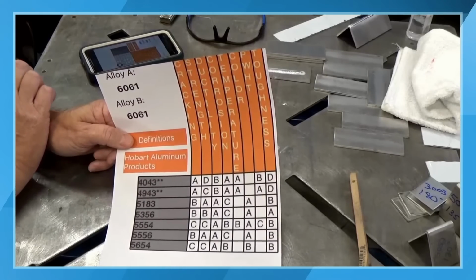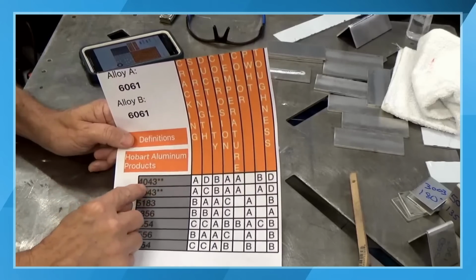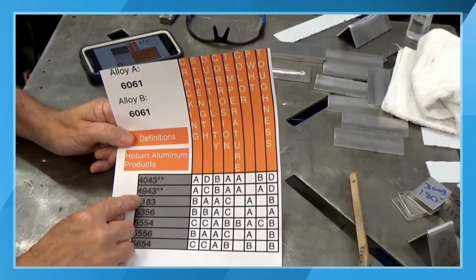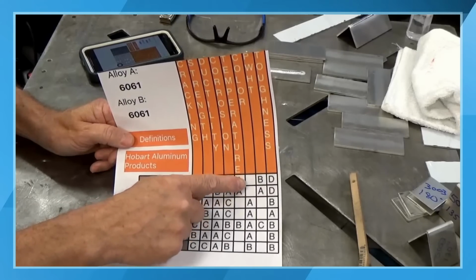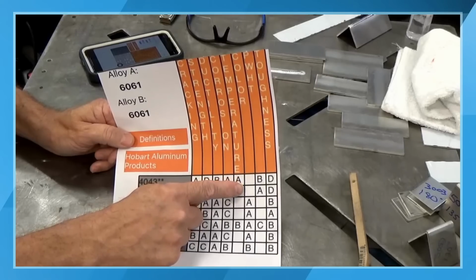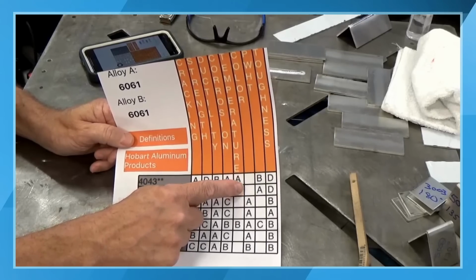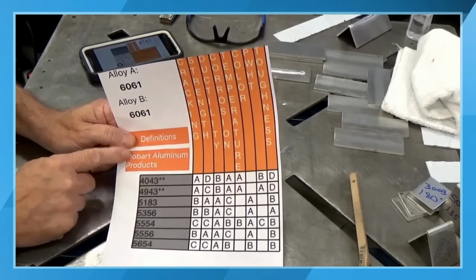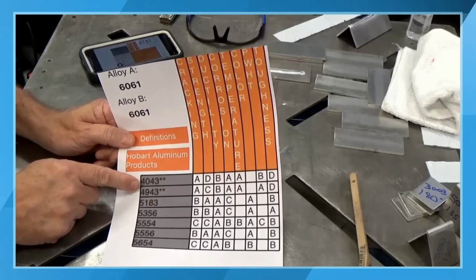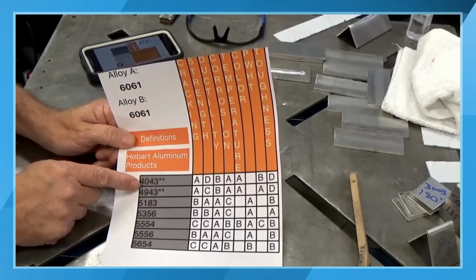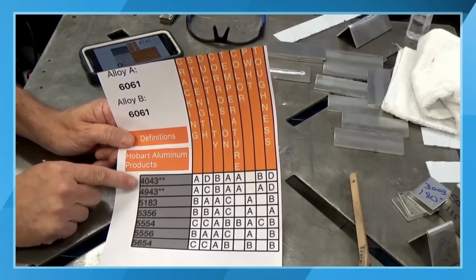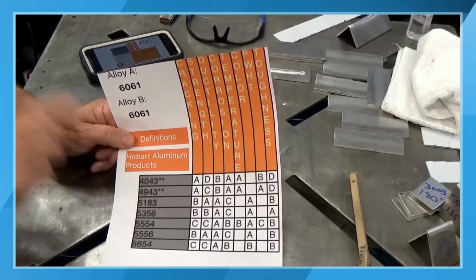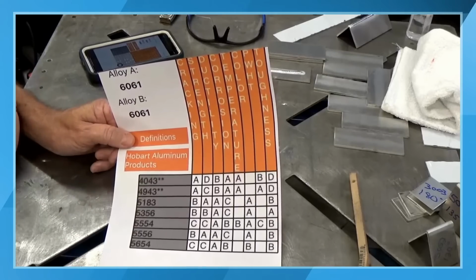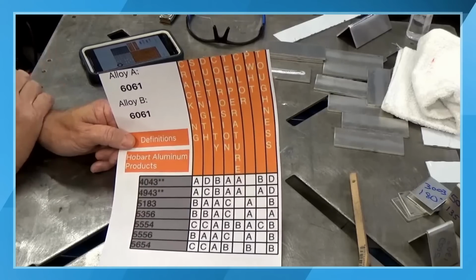Okay. So if you look here, 4043 and 4943, that box isn't even checked. There's not a letter high enough that will color match 4043 or 4943 to 6061. So if you're anodizing it and you use those two alloys or one of those two, it's going to be a completely different color at the weld puddle. Your weld bead is going to be completely different.